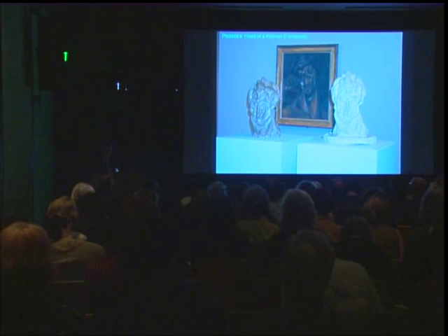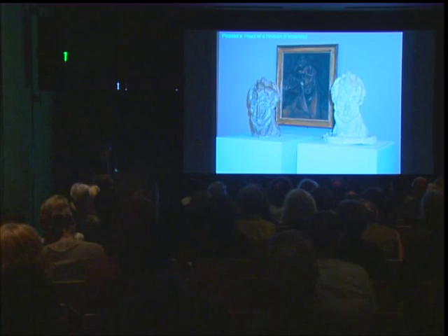The Picasso Head of Fernande exhibition, also shown here earlier this year, showed that having made his clay model in a burst of creative intensity, Picasso had relatively little, one could almost say very little, interest in what happened afterwards, as numerous bronze versions of it were cast over the next 50 years or so. Research started by Valerie Fletcher and Shelley Sturman continues, but it has been suggested that the earliest Fernande bronzes were less faithful to the form of the plasters than the later bronzes. In the latter, there is an improvement in exact replication that represents changes in foundry practices from sand casting to lost wax, and from piece molds to gelatin and silicone rubber molds.